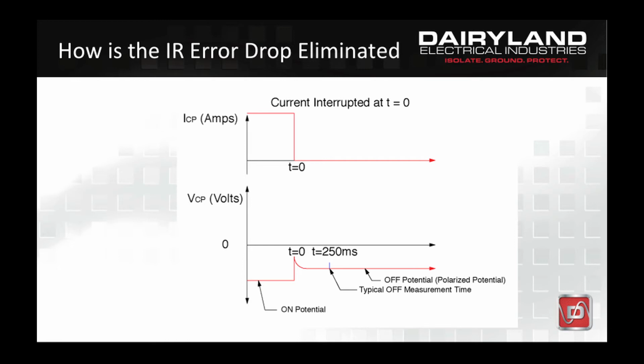In practice, since a transient voltage can occur the instant the rectifier current is turned off, the potential measurement is normally taken several hundred milliseconds after the rectifier current is interrupted to avoid measuring this potential voltage spike, which would introduce another error. The top graph shows the current being interrupted at a time t equals 0, and the bottom graph shows the off potential measurement being taken at t equals 250 milliseconds, a typical measuring delay time.